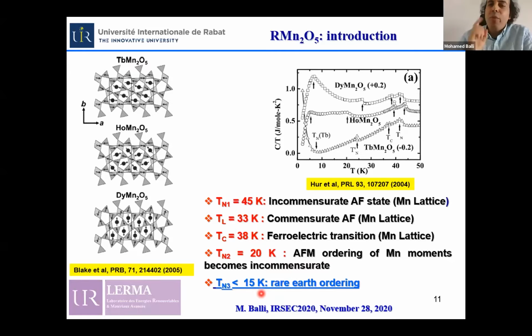There is also an important point I would like to mention concerning this family of materials. In fact, the magnetic moments of the manganese sublattice are strongly antiferromagnetically coupled in the AB plane, forming zigzags as shown in these figures. This makes the contribution of the manganese lattice to the overall magnetization of the materials marginal.